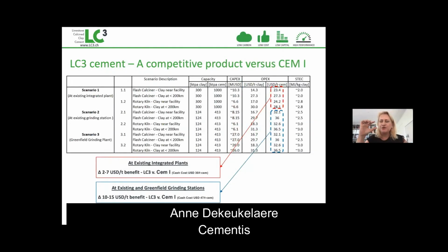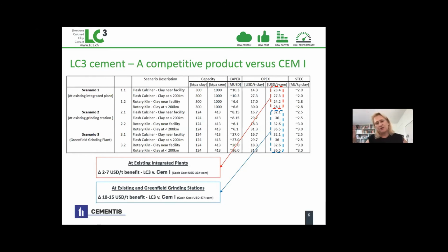The scenario where you produce LC3 in your plants, where you have access to your coal. Here, compared to the 30 USD of the OPC, producing LC3 will reduce your OPEX by 2 to 7 USD per ton. I think if I do the calculation, for the integrated plants, the $2 to $7, if you took say 5, then that's probably a 10% improvement in EBITDA. And maybe for the grinding station it is 10 to 20% depending on your pricing.